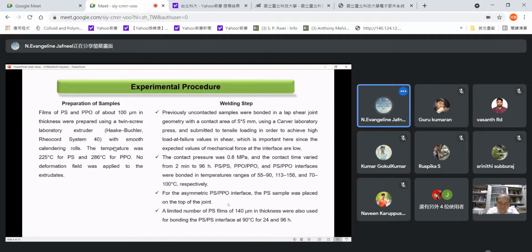Now the welding step. The contact pressure was 0.8 MPa and the contact time varied from 2 minutes to 96 hours. The bonding temperature ranged from 55 to 90 degrees Celsius for the PS-PS interface, 113 to 156 degrees Celsius for the PPO-PPO interface, and 70 to 100 degrees Celsius for the PS-PPO interfaces. A limited number of PS films of 140 micrometer in thickness were also used for bonding the PS-PS interface at 90 degrees Celsius for 24 and 96 hours.